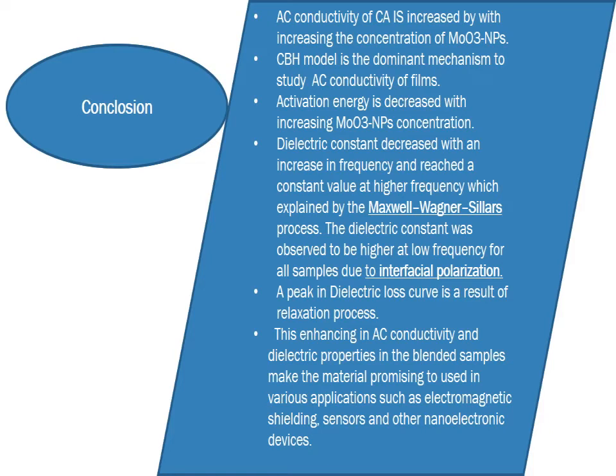The dielectric constant decreased with an increase in frequency and reached a constant value at high frequency, which is explained by the Maxwell-Wagner-Sillars process. The dielectric constant was observed to be higher at low frequency for all samples due to interfacial polarization. A peak in the dielectric loss curve is a result of a relaxation process.